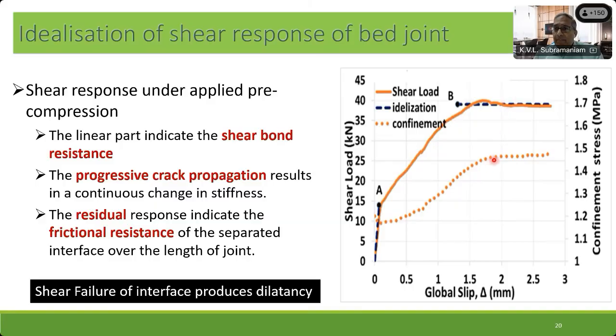At that point in time, if you look at the confining stress, the confining stress also becomes constant. So what is happening here? Why is the confinement stress increasing? As the crack forms in the interface, the crack that is formed is actually a rough crack. And as the two rough crack faces start to move relative to each other, dilation is produced. Whenever you have two rough surfaces slipping past each other, you will see an expansion that takes place. And that's exactly what's happening in this part here.